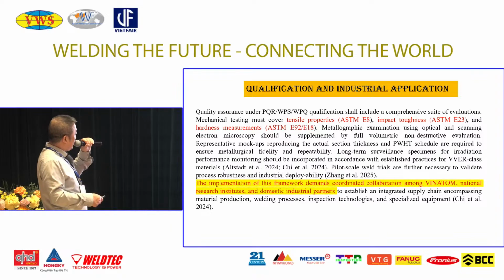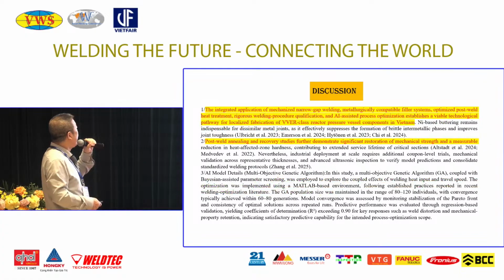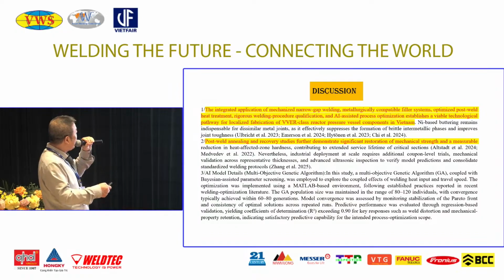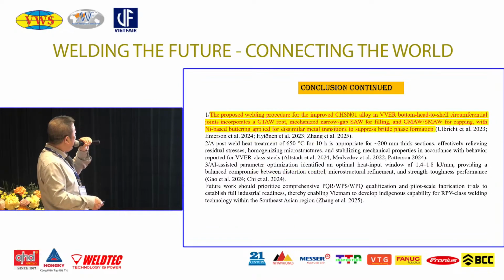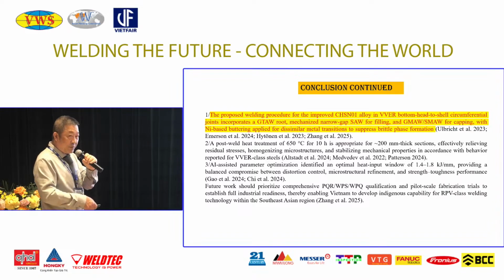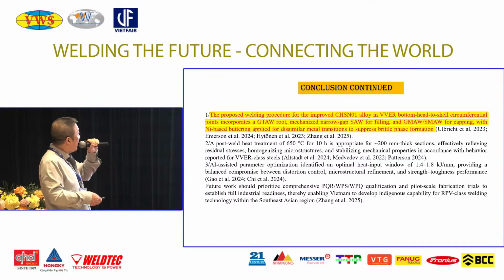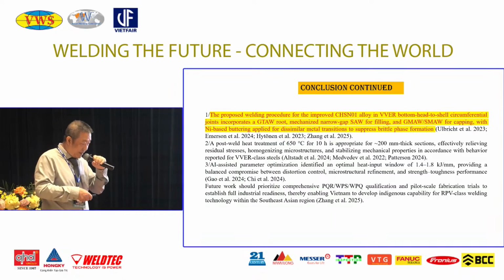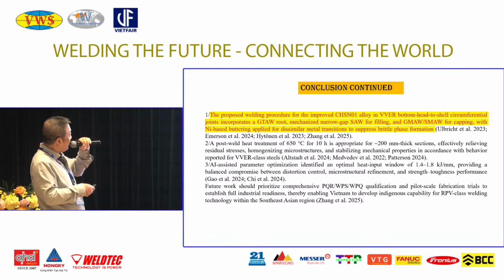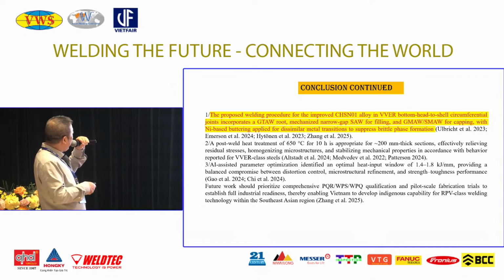And we also recommend some qualification for industrial application. Finally, discussion, as you can see in the slide. And conclusion: the proposed welding procedure for the improved alloy in the bottom head to shell circumferential joint incorporates a GTAW root, mechanized narrow gap SAW for filling, and GMAW for capping, with nickel-based buttering applied for the dissimilar metal transition to suppress brittle phase formation. Thank you for your presentation.